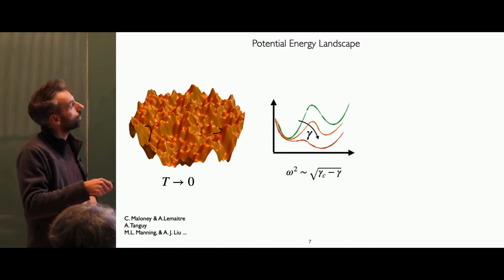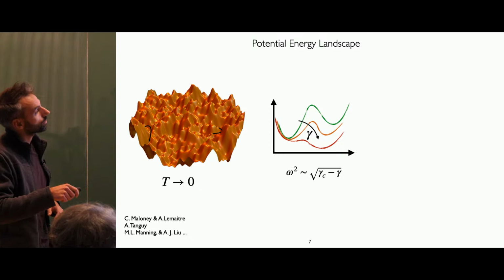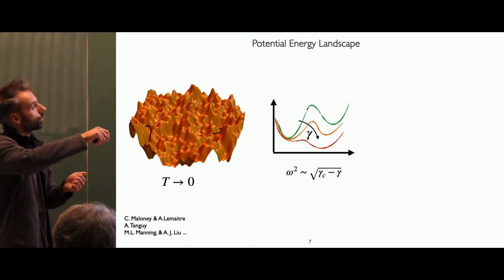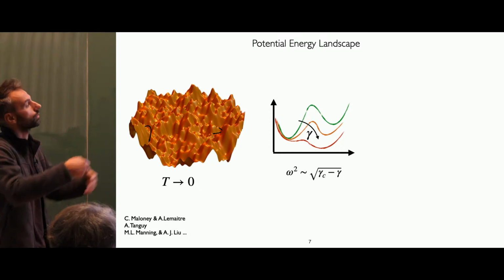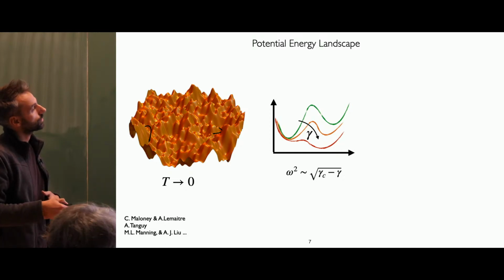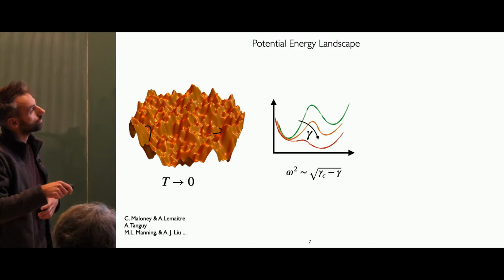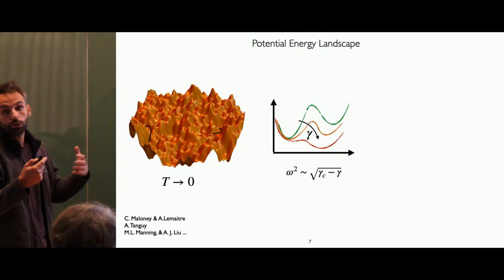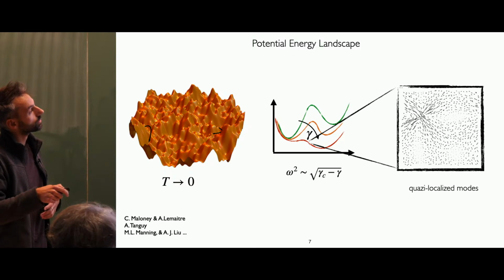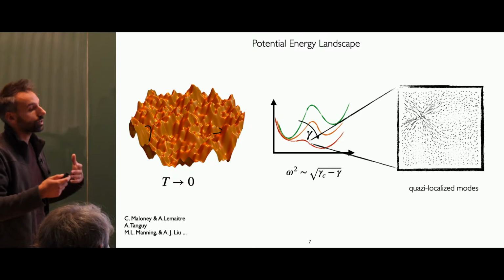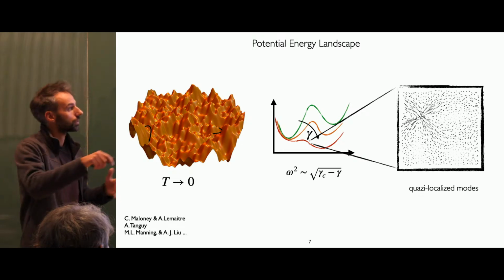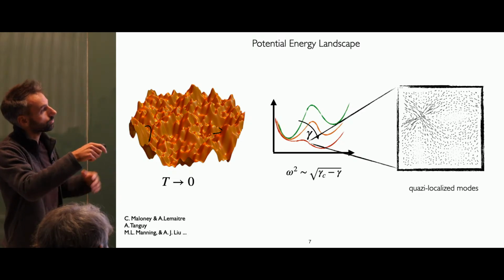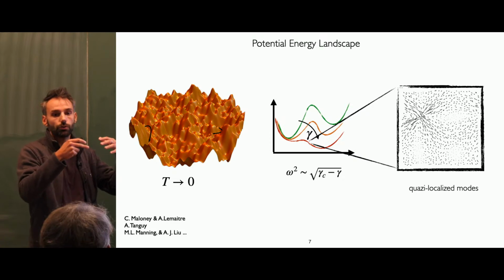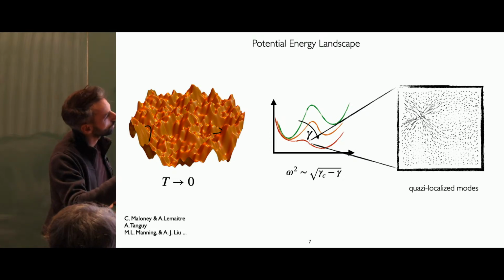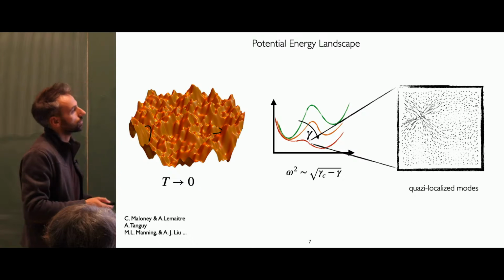And so in terms of the landscape picture, here gamma is the strain, you start to deform your solid, and at some point there is a critical strain where the system will flow and produce some plasticity. And when you look at the curvature of the landscape, what will be the unstable mode that makes you flow, if you look in space how it looks, indeed it's not something delocalized everywhere in the system, it's very localized, and it's really particles that will undergo a small shear transformation. So some particles will go out and go in and release some stress.